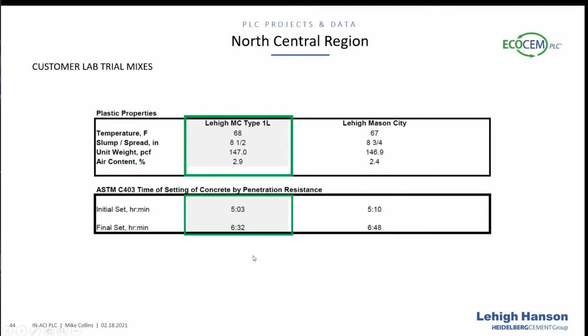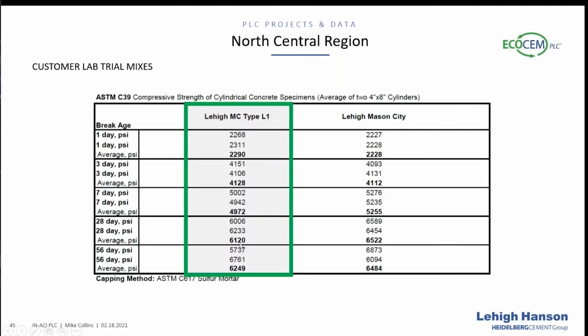And what they found again was things that we have seen in the Mitchell lab. So in terms of time of set, just a hair faster on the initial set, and about 16 minutes faster on the final set. So again, things that we've seen out of the Midwest, the Central Region cements, we're starting to see again out of those North Central Region cements.